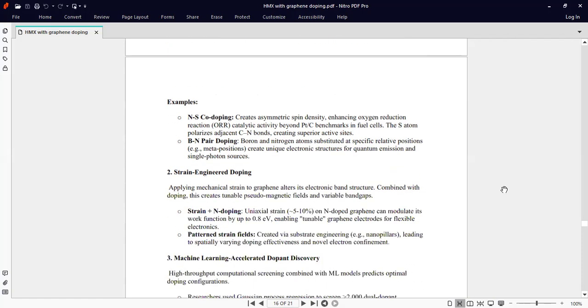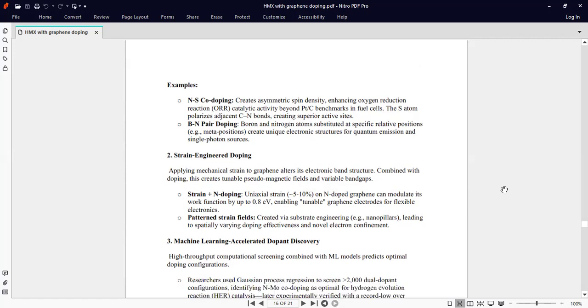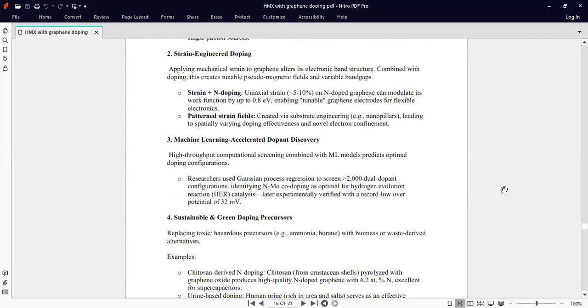Boron-nitrogen pair doping: boron and nitrogen atoms substituted at specific relative positions, the meta position, create unique electronic structures for quantum emission and single-photon sources. Strain engineered doping: applying mechanical strain to graphene alters its electronic structure. Combined with doping, this creates tunable pseudomagnetic fields and variable band gaps.